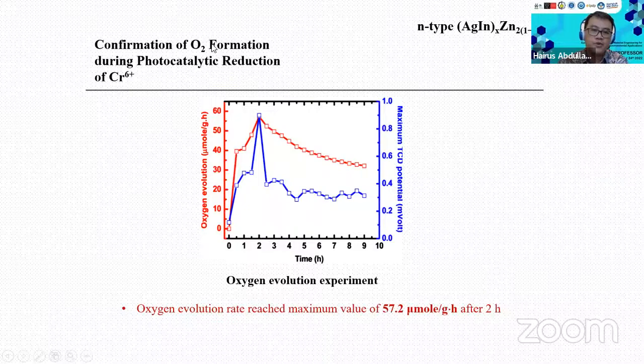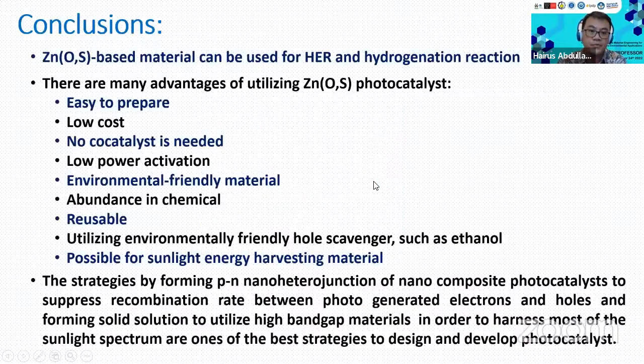And this is the proof for the oxygen formation during the reaction. The electron is used for the chromium reduction, and the hole is used for water oxidation. Then the product is oxygen, and we found that there is oxygen during the reaction.